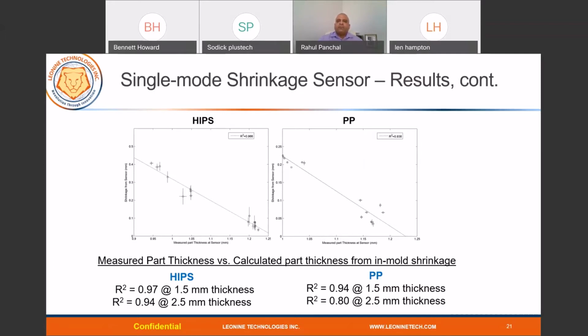So polypropylene being a semi-crystalline material, it shrinks, and the bigger the cavity thickness, the higher the shrinkage. And in semi-crystalline materials, it shrinks faster and the magnitude is larger. Also, the semi-crystalline material, especially polypropylene, will take a certain time to change its dimensions. So we assume that could be the reason.